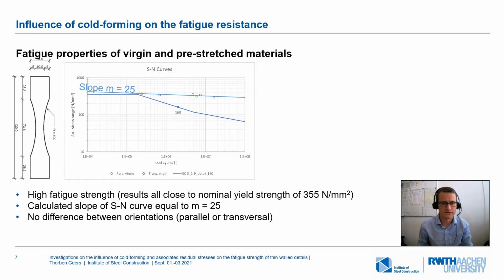The results of the fatigue test with given specimen geometry are now shown here. In this and the following diagram, the SN curve for the highest notch detail 160 according to Eurocode 3 is given for orientation purposes. The results of the fatigue tests are all in the range of the nominal yield stress of 355 MPa. The slope of the SN curve is approximately 25.